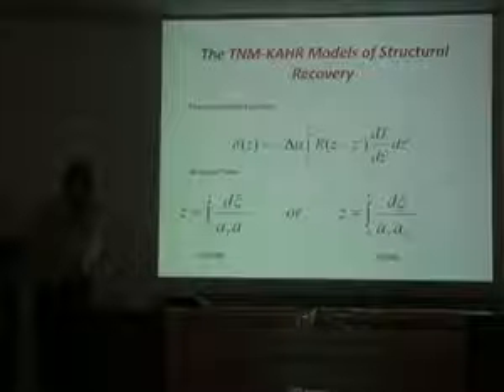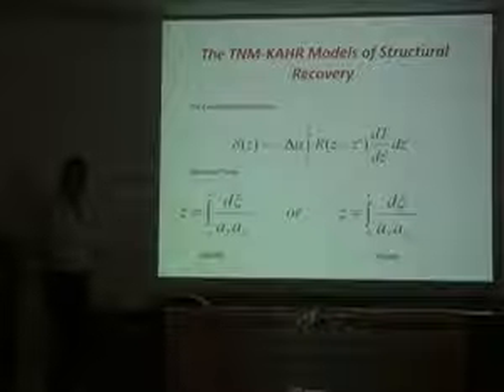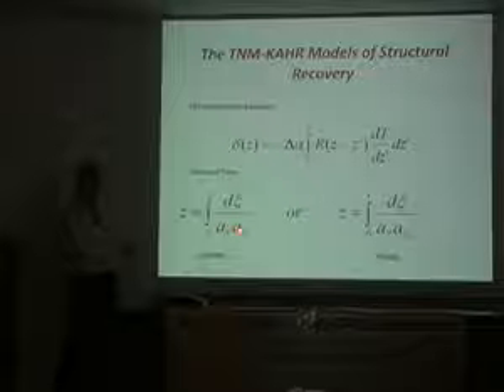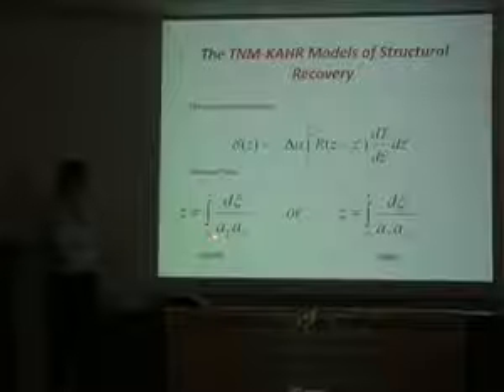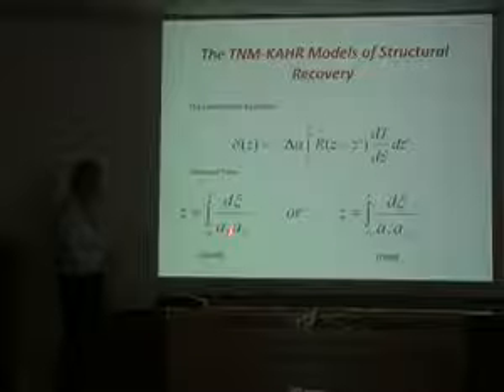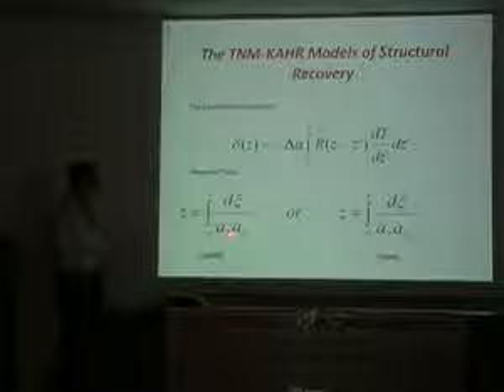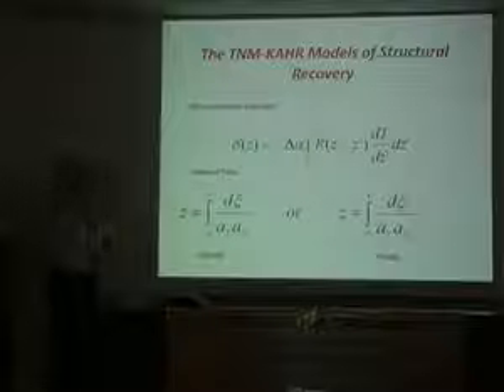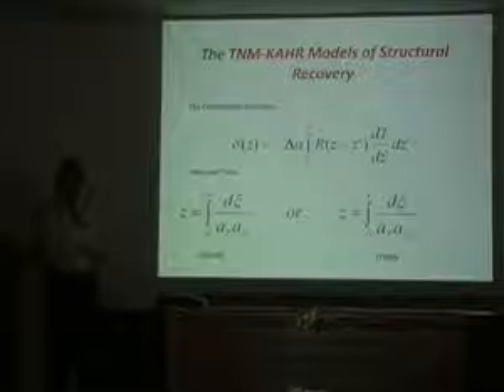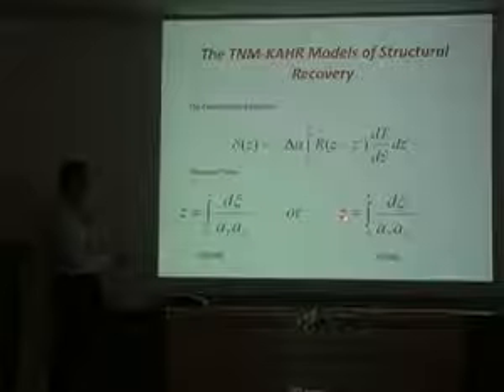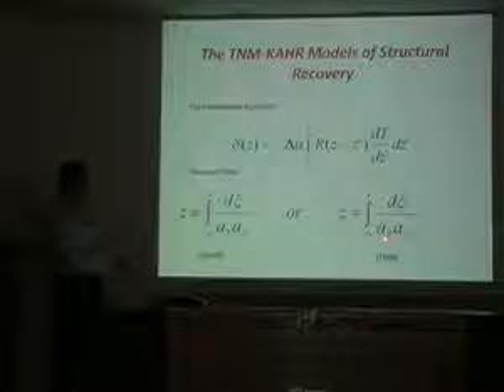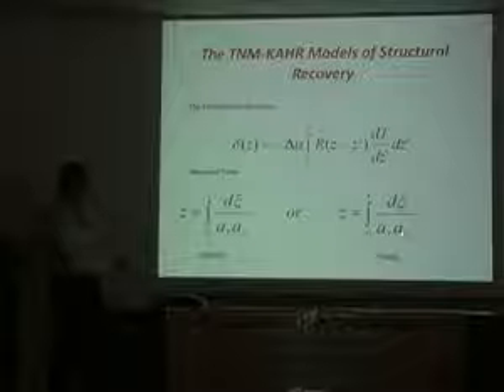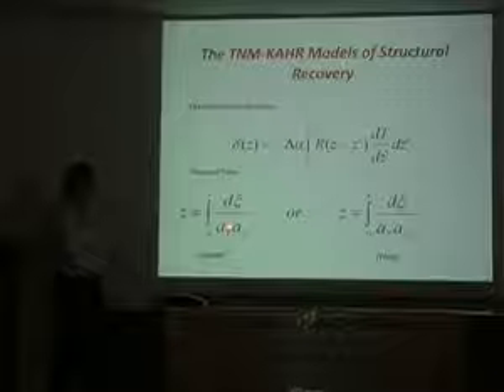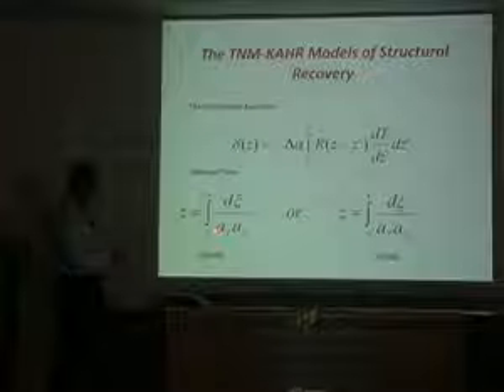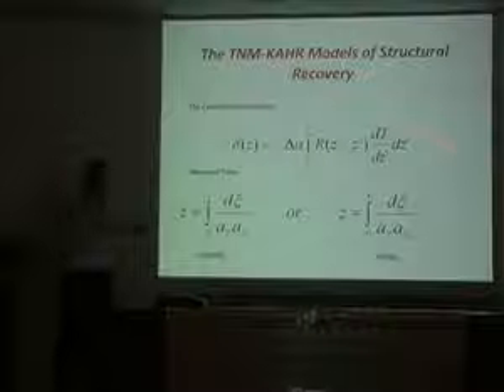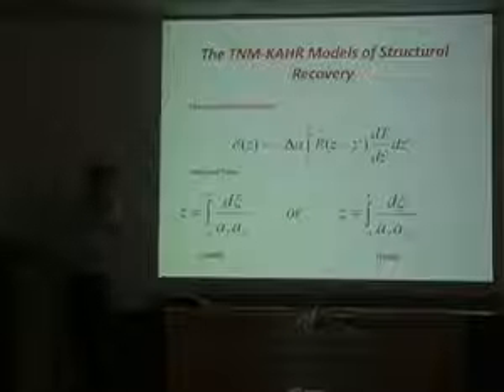How do you define A_T and A_delta? I'll go to that, but this is a temperature shift factor. You could use something like a WLF or Vogel-Fulcher temperature shift factor. Generally, in the TNM model, they use an activated process, but just an apparent activation energy. So, and this is what the reduced time is defined as for the TNM model. It's still A_T, so a temperature shift factor and a structure shift factor. The details of these will not be the same in form, but mathematically these turn out to be the same models, okay?